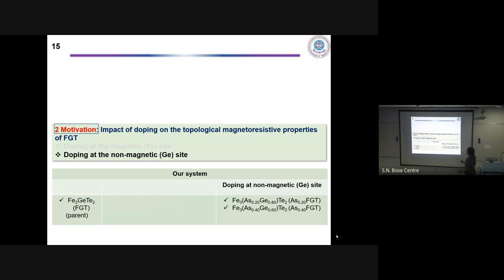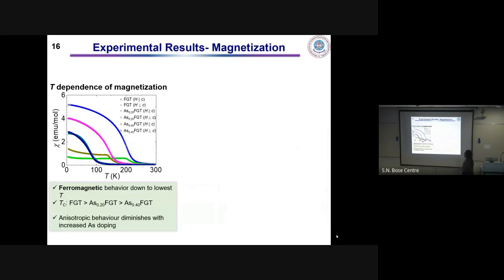So these are the concentrations for the doping part in Fe3GeTe2. These are the two concentrations we could grow, and what we observed from the temperature dependence of magnetization is that this blue curve corresponds to the FGT when the magnetic field is in the out of plane direction. The other one corresponds again to the FGT magnetic susceptibility versus temperature curve when the magnetic field is perpendicular to the z-axis. Same behavior, you see a large difference between the two. But when we increase the arsenic concentration, we see a continuous reduction of the TC, and the anisotropic behavior is also diminished with increasing arsenic doping.